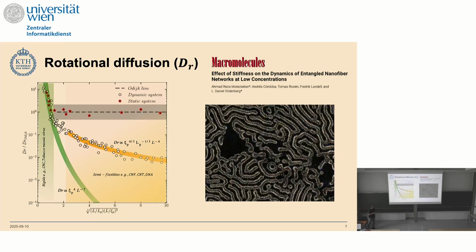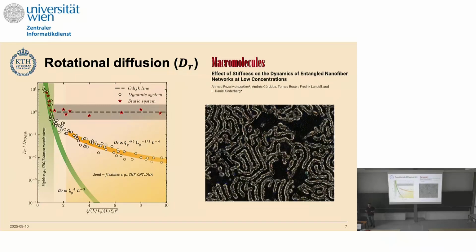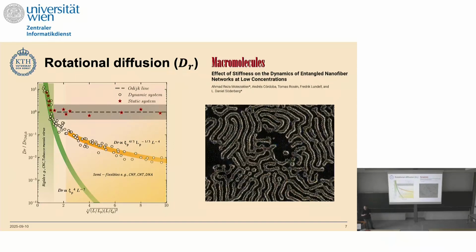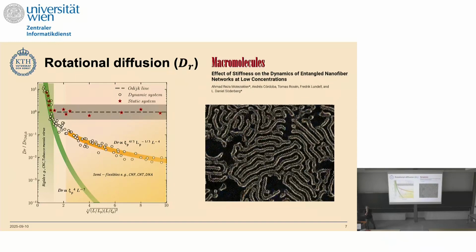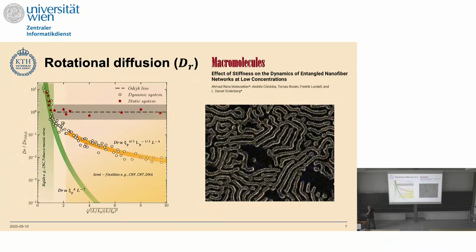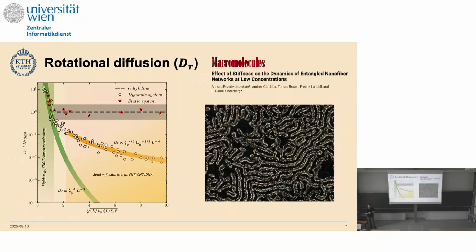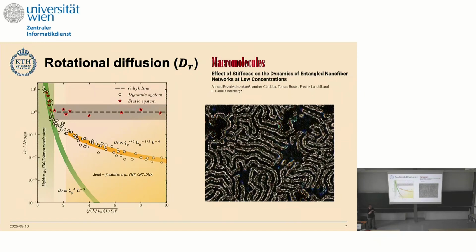One of the main points of this paper was to analyze the tubes in the system. What you see here are the empty spaces between the polymers, which change in size, rotate, and are not stable. We have been able to estimate the size of these tubes.